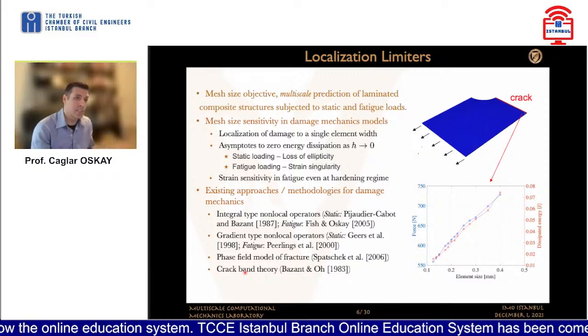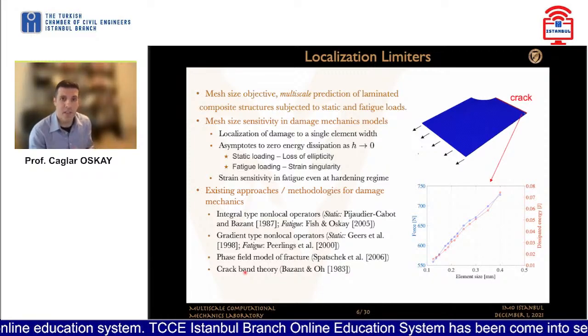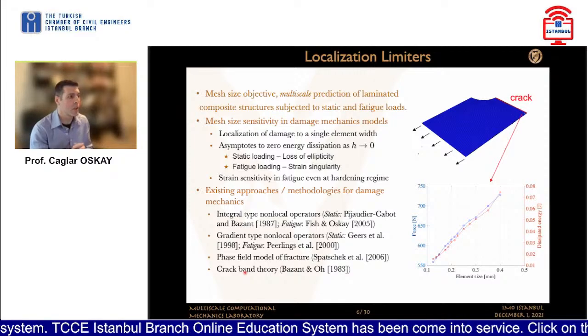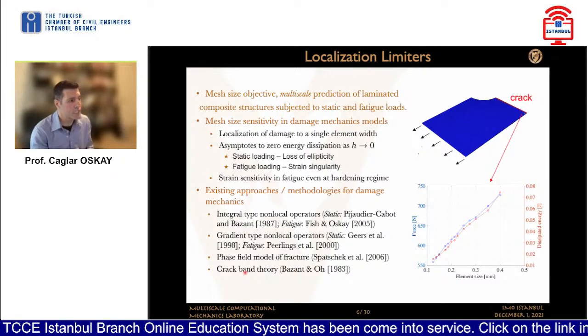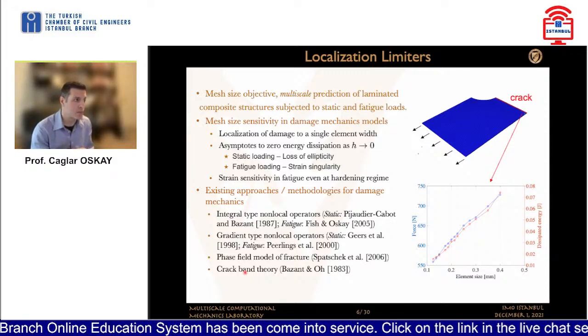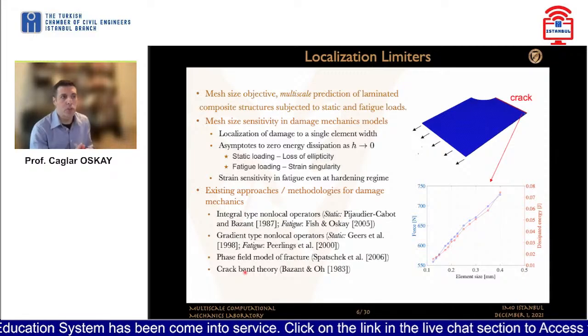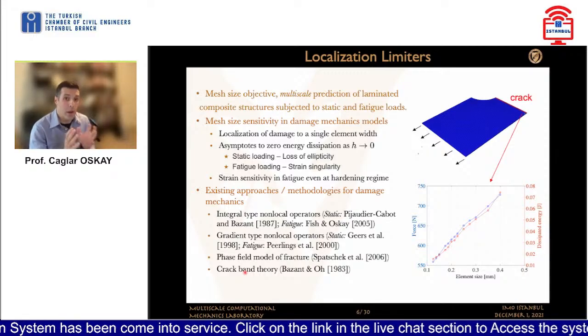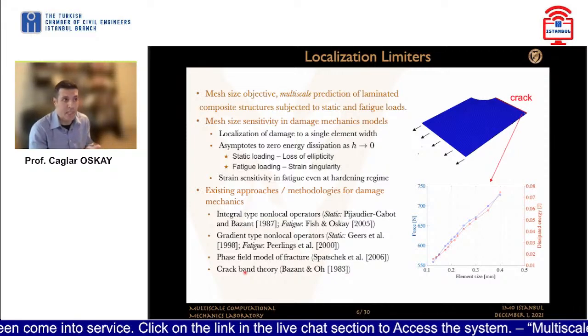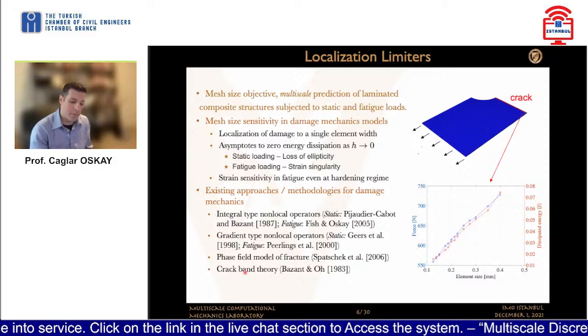For static and fatigue loading conditions, the reasons are quite different. In static loading, the ellipticity of the underlying partial differential equations is lost once you start going into the softening regime. Whereas in fatigue loading, even in the hardening regime, fatigue models typically demonstrate mesh size sensitivity due to the inability to capture strain singularity. So there have been quite a few approaches that attack this problem. What we wanted to do is to make sure that we develop an approach that is valid for multiscale simulations, and valid by leveraging the principles of multiscale analysis.